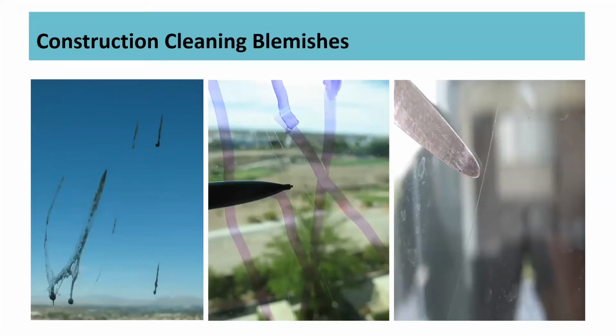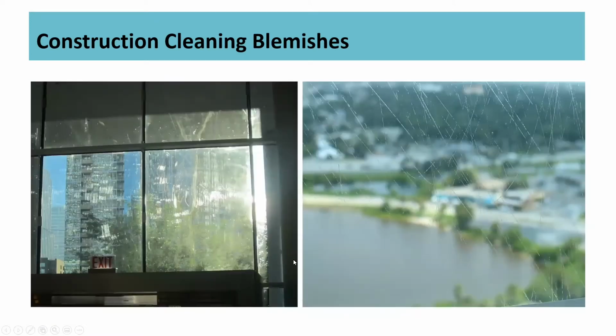Construction cleaning, you would gather, should improve the overall appearance of the project before handing it over to the owner or developer. But we're finding that construction cleaning accounts for most of the construction blemish projects that we get pulled into. Some of these seem pretty benign. We're zoomed in pretty far. The scratches are pretty faint in these three photographs. There's some debris that's hit the glass on the left-hand photograph during construction.